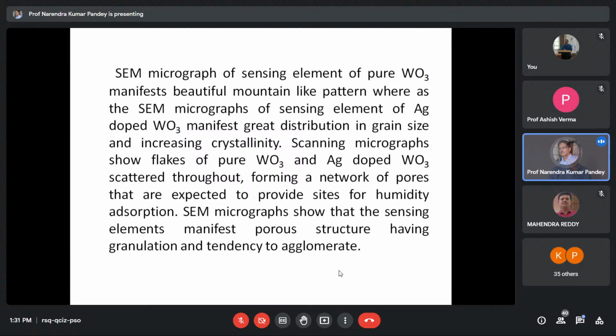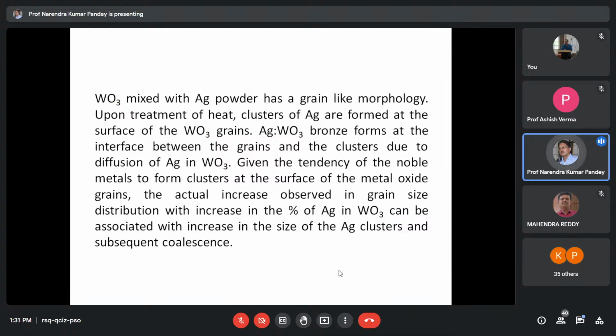SEM micrographs show that the sensing elements manifest a porous structure having a granulation tendency. Similarly, they have a grain-like morphology. WO3 mixed with Ag powder has a grain-like morphology. Upon treatment to heat, clusters of Ag are formed at the surface of WO3 grains. Ag WO3 bronze forms at the interface between the grains and clusters due to diffusion of Ag in WO3.